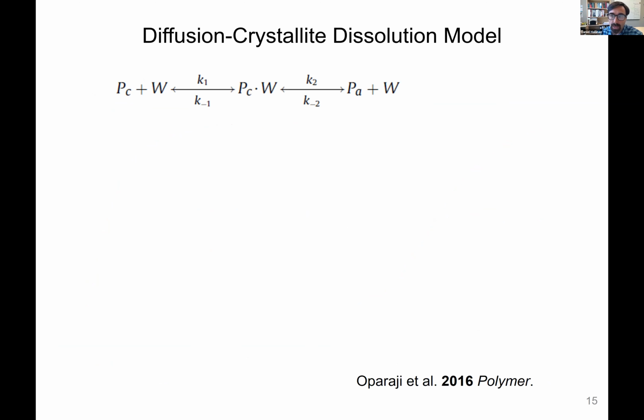So to try to understand why we saw non-Fickian diffusion at low humidities and then Fickian diffusion at higher humidities, we developed a very simple sort of reaction-based model, although it's probably not technically truly a reaction. So we have polymer crystals present in the PEO, and we have water molecules diffusing into the material. We proposed that the water molecules get immobilized as they dissolve the polymer crystals, and then once the polymer crystals are dissolved, they are amorphous. The polymer is now amorphous and the water molecules are again free to diffuse.